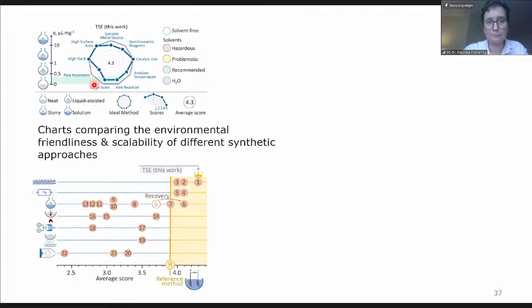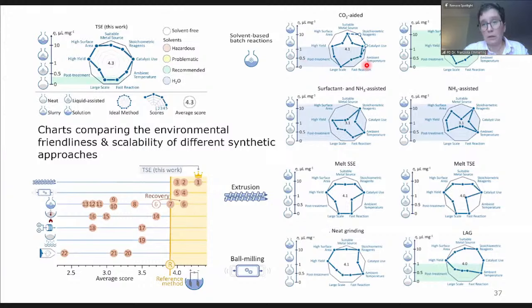So we wanted to have a fast reaction. We wanted to use less solvent, small amounts of solvent. We wanted to have a high surface area and so on. And then you can see here, this is the chart for our process, but we can also compare it to others where we have solvent reaction, but also other extrusion reaction or ball milling. And in this case, of course, you might have guessed it, our process is by far the environmentally friendliest one, and also the one that reaches the highest surface area.